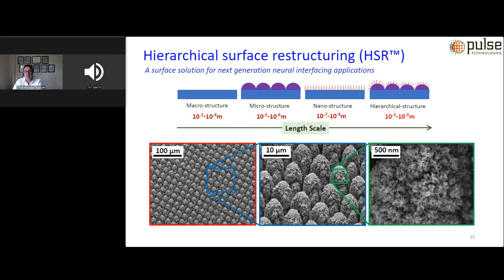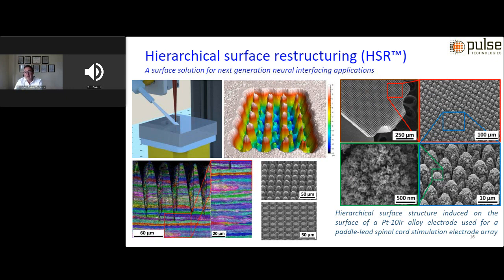And you could see some examples of scanning electron microscope images of these hierarchical structures that have been produced on the surface of electrodes. Over the last several years, we have developed the applicability and performance benefits of femtosecond laser hierarchical surface restructuring technology. We have explored the tunability of performance as a function of several readily accessible laser parameters on a wide array of electrode materials and geometries for a large number of devices and applications. As an example, on the top right section of the slide, you can see the hierarchical surface structure that is induced on the surface of a platinum 10% iridium alloy electrode that is used for a paddle lead spinal cord stimulation electrode array.